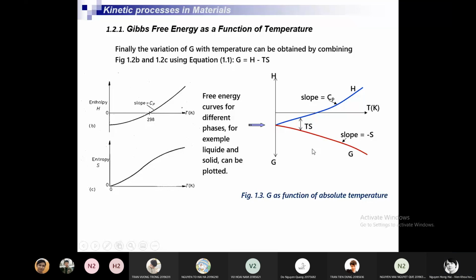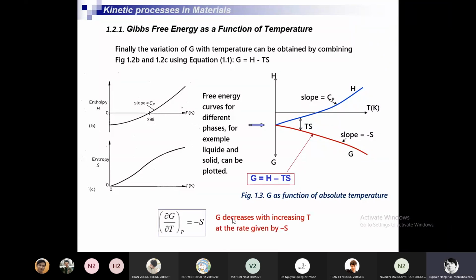Very important conclusion: the free energy of the system decreases with temperature. So we have this G equal to H minus TS, which gives the free energy. And G decreases with increasing T, and the rate of decrease is given by minus S. So I can say that the slope of this curve is minus S.